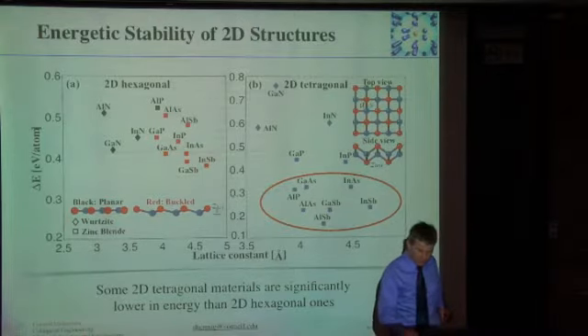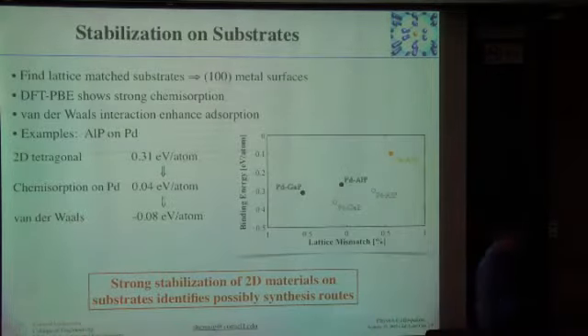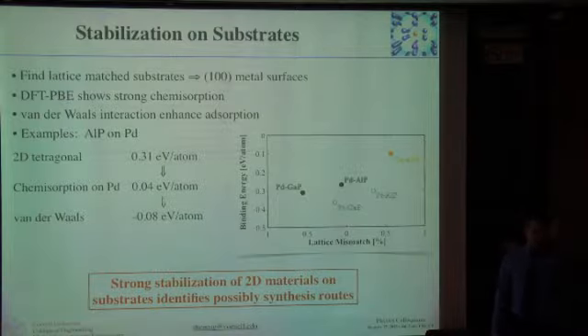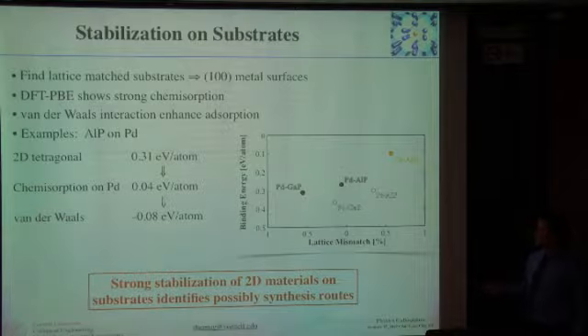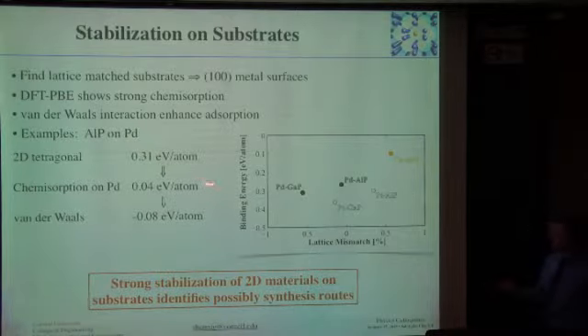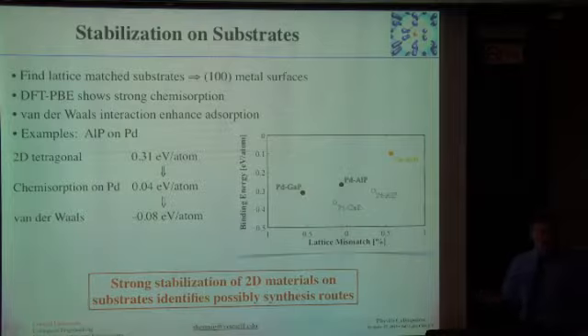What's even more interesting is if you now take those tetragonal materials, and I guess you could do the same thing with the hexagonal materials, and stick them on the right substrate, you could really stabilize the materials. So we take our 2D tetragonal aluminum phosphide, we identify the material which is closely lattice matched, the 100 surface of palladium, stick it on there, the energy drops from 0.3 electron volt per atom to 0.04, to pretty much close to 0. If we then also include van der Waals interaction in our calculation, which are often neglected, we get it that it's actually even more stable than the bulk form.